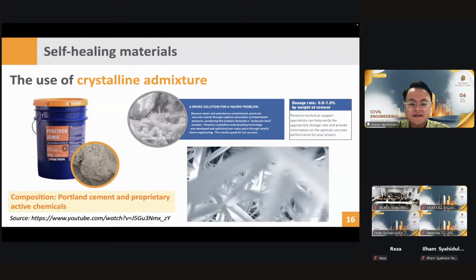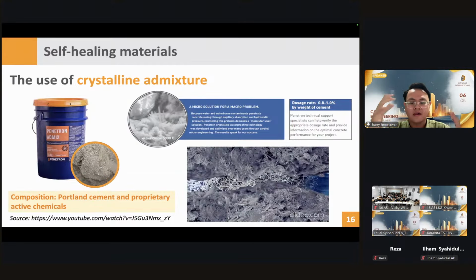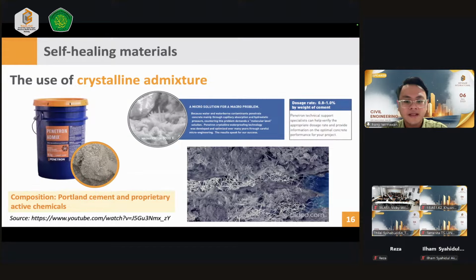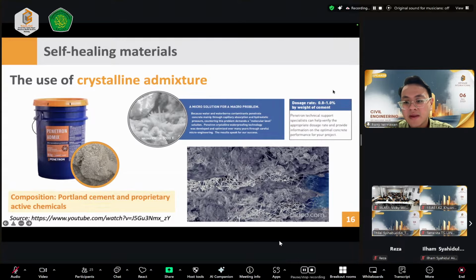And later on, the crystals will grow as a whole matrix, and it becomes one integrity with the concrete materials. And imagine now from the video, if you have another crack forming on another side of the matrix, later another formation of the crystals will occur. So the use of the crystalline admixture is based on the generation of crystallization. It will generate a lot of crystals, which is based also on calcium carbonate, in order to block the cracks. So the water could not penetrate anymore into the cracks because of the clogging by the crystals. And in the dosage, typically we use this crystalline admixture in the range of 0.8 up to 1% by weight of the cement.